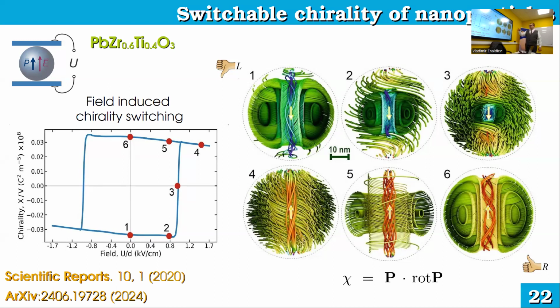It's, again, a hysteresis loop. We go through electric field, but now we measure not polarization but chirality. Please note it's a volumetric value, so as I said, it's an integral value over the volume of the nanoparticle, but colors encode chirality at a point. First of all, you see that chirality is unbalanced. Some parts of the nanoparticle contribute more to chirality than other parts. For example, it's easy to see that the core contributes more than the periphery. But if this core is negative, the periphery still can give a pretty big positive value. For example, for state 3, you see it's 0, because part of the core is negative, part of the core is positive, and they compensate.